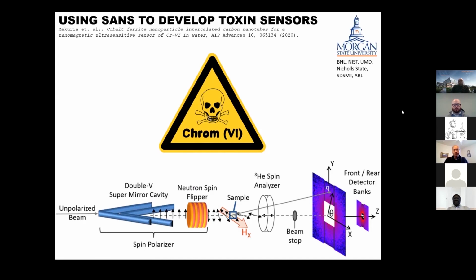So the Morgan State-led collaboration, which involved Seifu and Mercuria, focused on looking at the magnetic response of a magnetic nanoparticle intercalated carbon nanotube whenever it's infused with small amounts of the hexavalent chromium. The interest in this nanocomposite system is based on evidence that these systems can exhibit enhanced magnetization. So a completely different phenomenon to try and detect hexavalent chromium, which has its own magnetic properties.